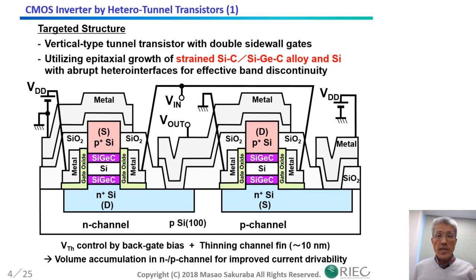A tunnel transistor is a candidate of low voltage and highly efficient switching device for next generation. Aiming at the vertical channel type seems to be natural for me by using epitaxy. In order to realize this device, many issues can be imagined. For example, the most difficult process seems to be fine pattern formation of 10 nanometer order fin or wire structures. Additionally, gate stack formation for extremely low voltage switching is necessary. Anyway, from the epitaxy side, low temperature epitaxy has an important role in definition of channel length and abrupt doping profile.